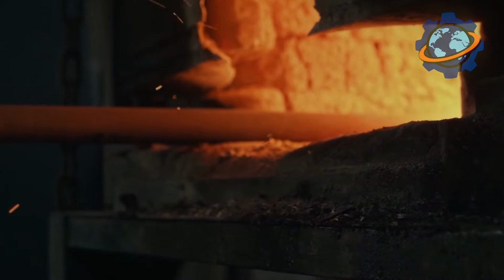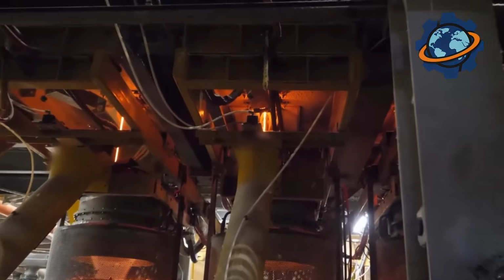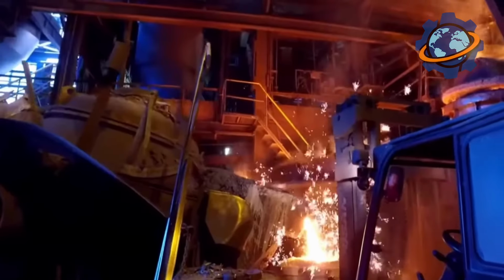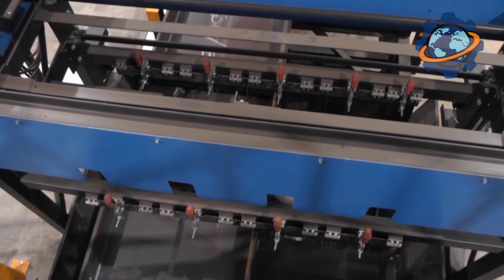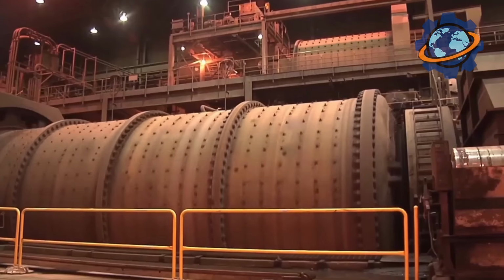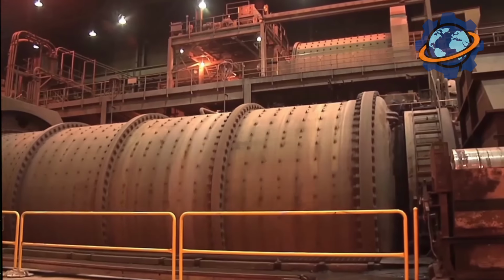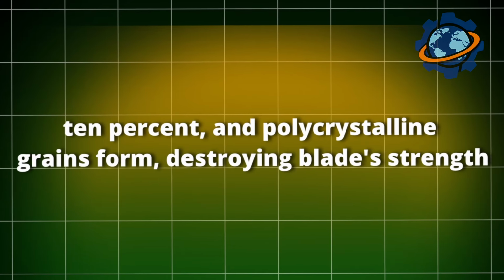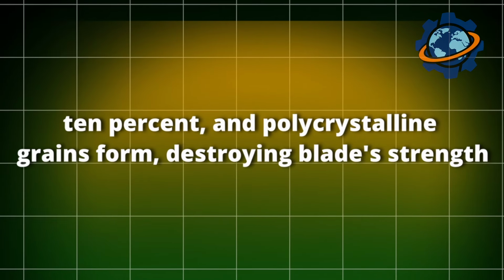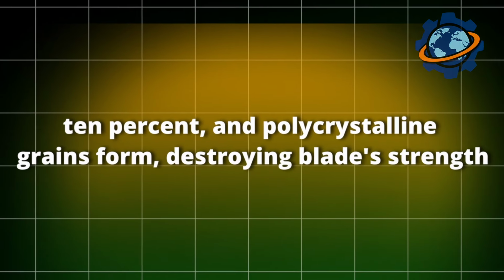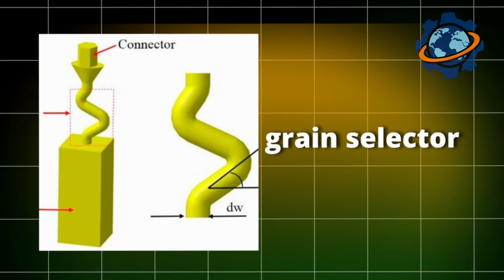As the mold descends, metal solidifies from bottom upward in a razor-thin freezing front. This directional cooling forces crystal growth in one direction only, upward, eliminating horizontal grain boundaries where cracks normally form. The process takes 14 hours for a 4-inch blade. Rush it by even 10% and polycrystalline grains form, destroying blade strength. But here's where physics becomes art.